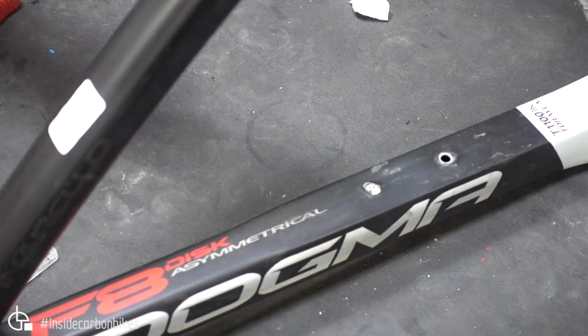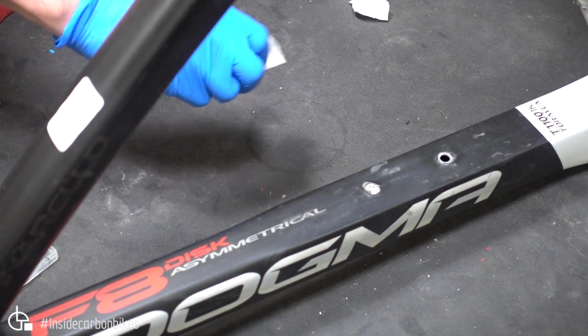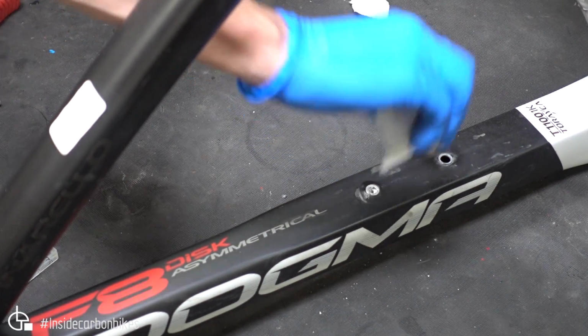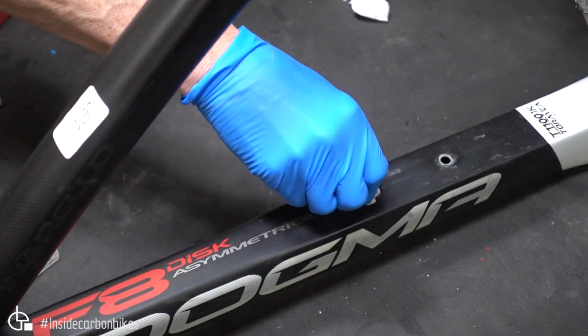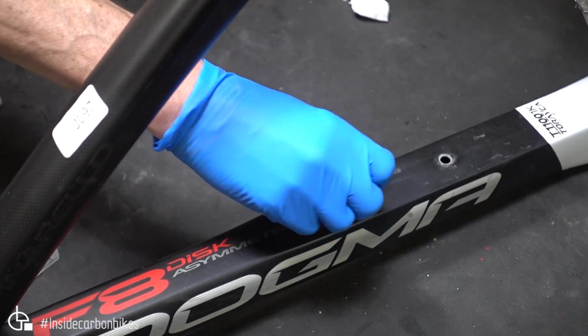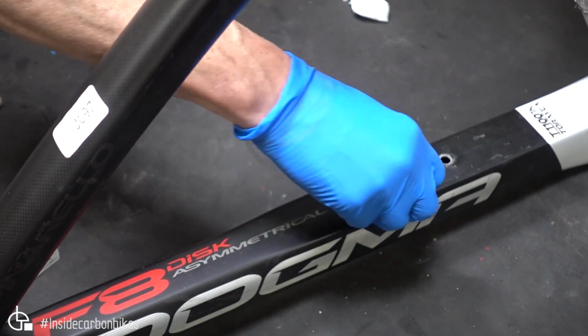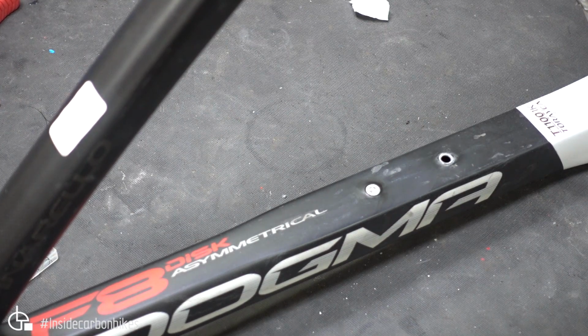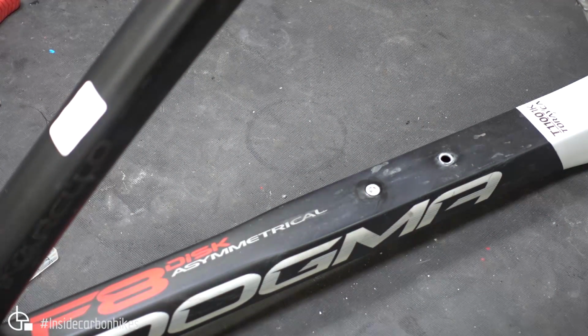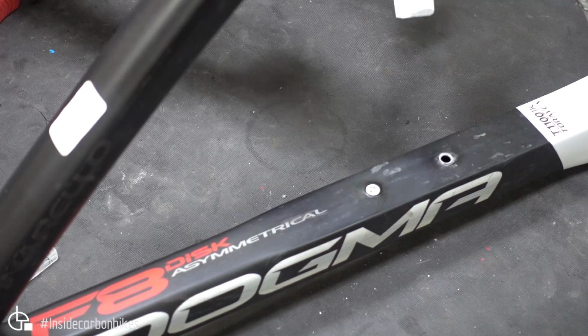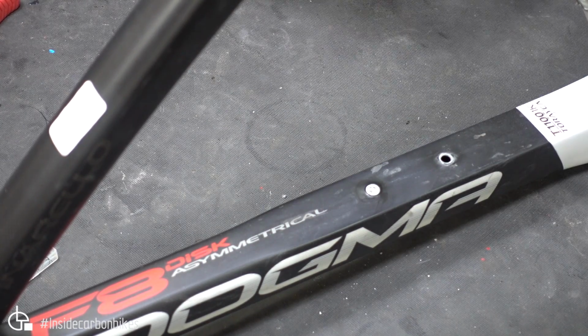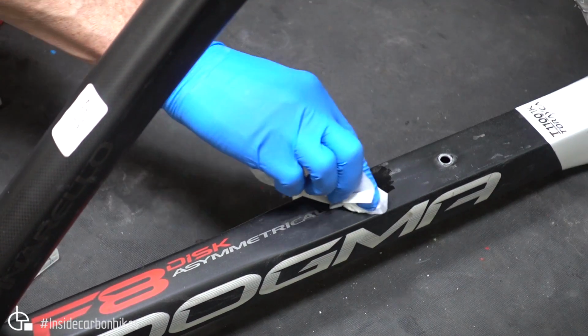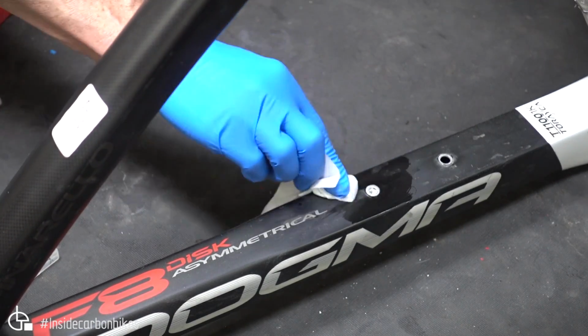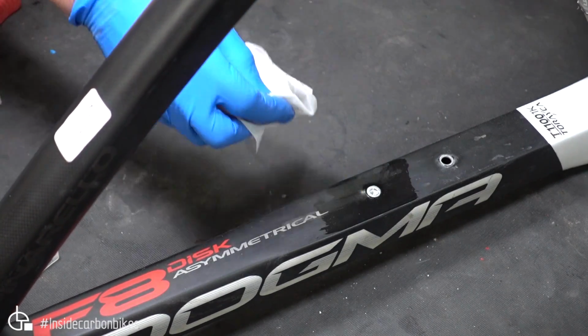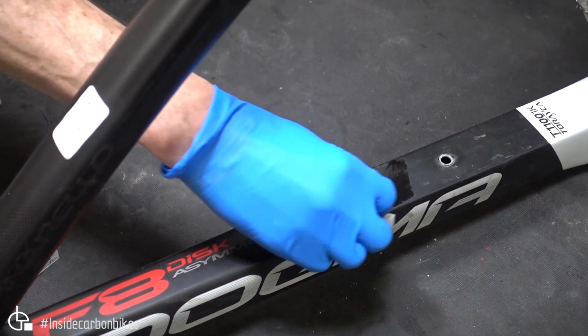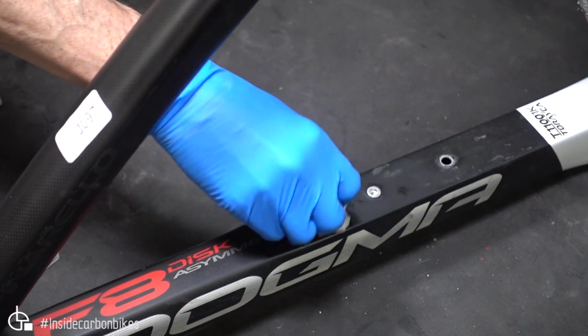The last step now is just to clean off any of the excess epoxy on the outside surface, which again we'll do with a tissue and some isopropyl alcohol on the surface. We'll remove any of the residue, and after cleaning up, it's ready to use. Now, I can't stress enough the importance of putting that adhesive down, because in the factory they don't do it, and that's what exacerbates this galvanic corrosion at that interface. Because you've got aluminium in direct contact with carbon, you're inviting problems. As soon as you get moisture in that interface, you're going to have corrosion.